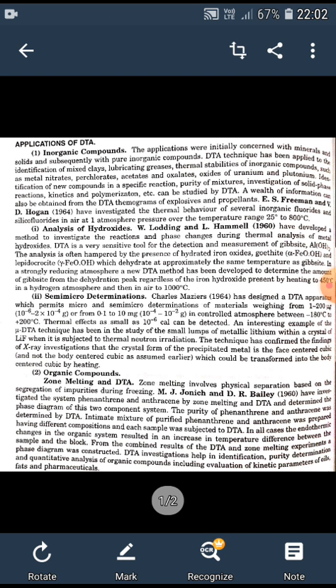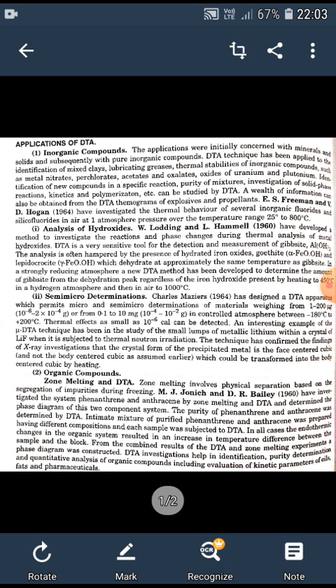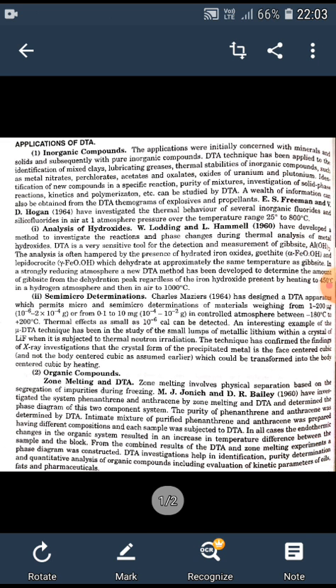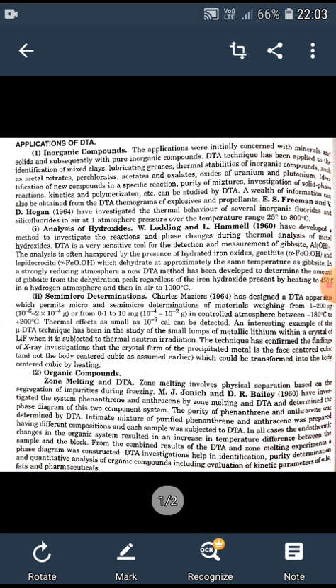An example of this technique has been in the study of small lumps of metallic lithium within a crystal of lithium fluoride when it is subjected to thermal neutron irradiation. The technique has confirmed the findings that the crystal form of the precipitated metal is the face-centered cubic, which could be transformed into the body-centered cubic by heating.